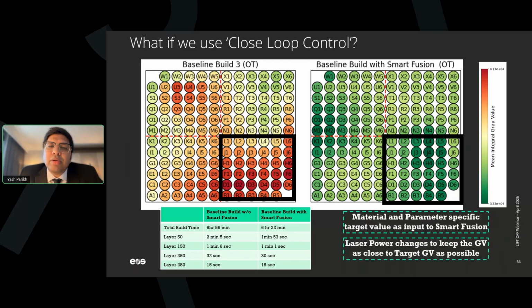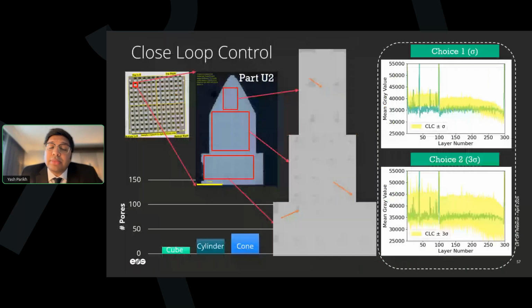So we did split open the same U3, this time U2, and looked at what happens to the porosity and all of that. And you can see what we found, the signature, very constant, very stable, because the set gray value was like 41,000. Anything above that is not there, except layer 100, which I told you about. And it auto corrects it. So everything is now very stable. At 2 sigma, at 3 sigma choice 2, everything is almost qualifying in the case of closed loop control. So now go to the next one.